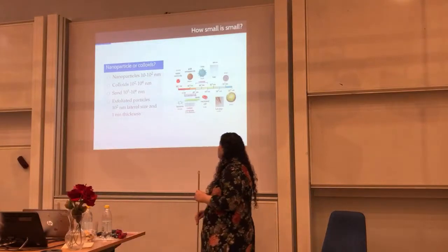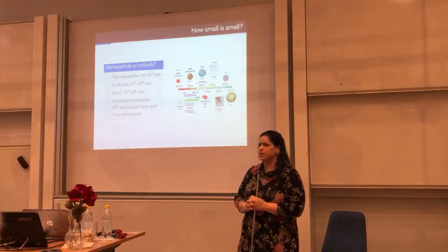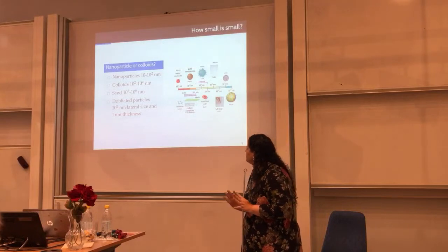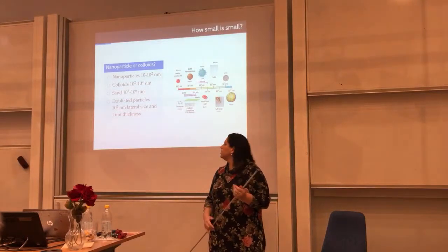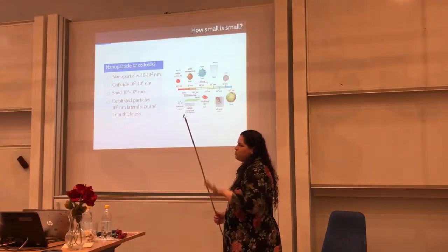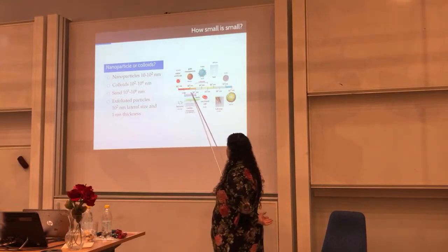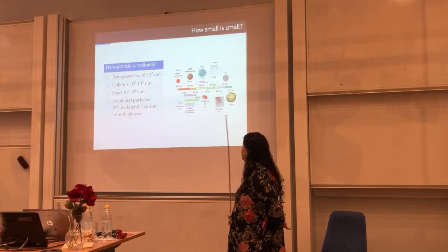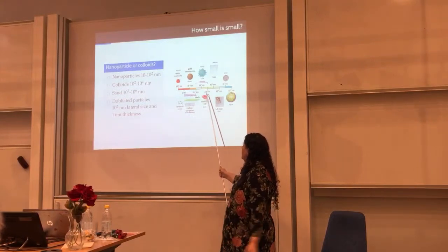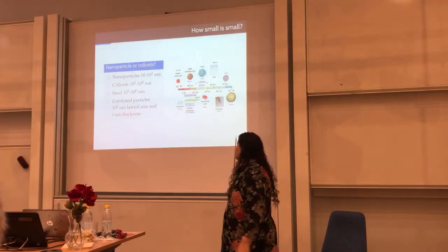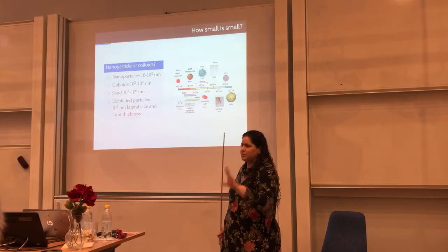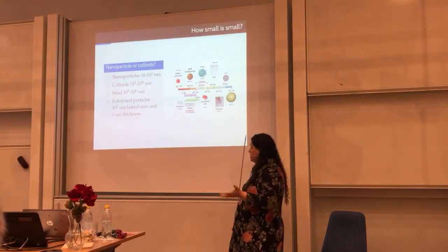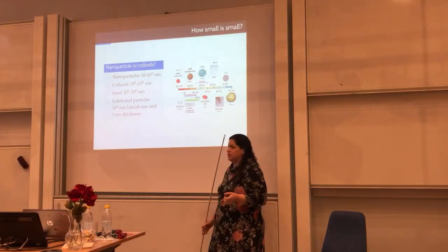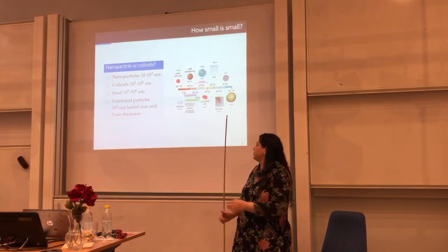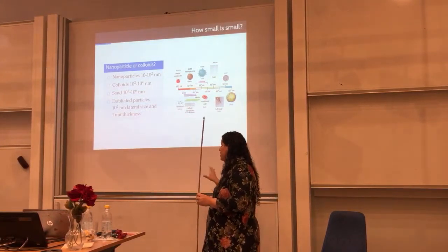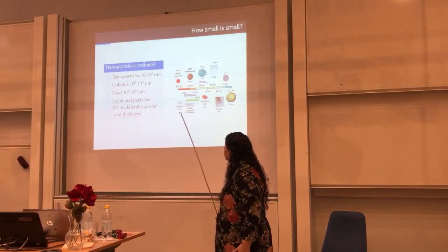We are talking about very, very small materials when we exfoliate them in water. We wish to give you a perspective on how small we are talking about. We are located somewhere in between nanoparticles and colloids. In the range from 1 nanometer to 100 nanometers, you have nanomaterials. And above that, up to 10^4 nanometers, you have colloids. So we are somewhere there. We will have colloids and nanoparticles in the dispersions, because one of the disadvantages of liquid phase exfoliation is that you have a wide range of particle sizes when you are exfoliating. There are methods to segregate and separate the particles, but I didn't use them in my thesis.